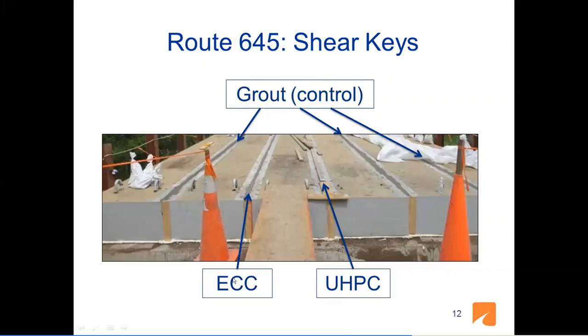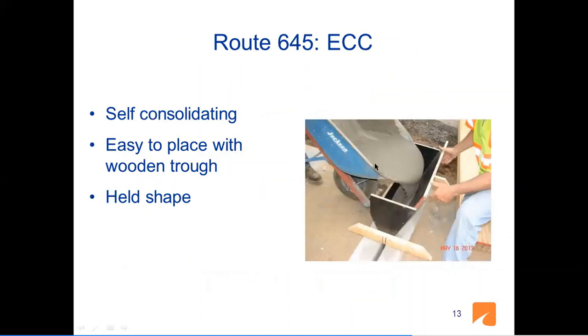But we were very happy with the ECC. As you see here, we made a trough, and we put the trough on the shear key opening, a very narrow opening. And then, as you see, it is self-consolidating, flowing very easily. And then it did hold the shape. So it went very well.